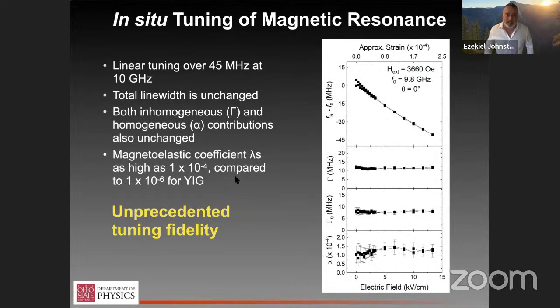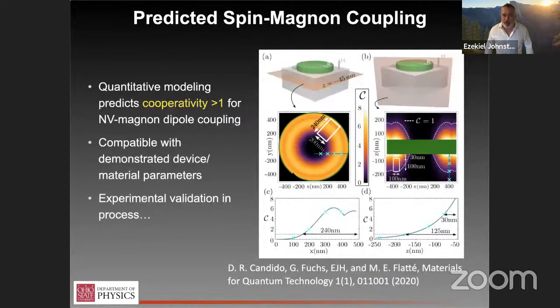And so in fact, this metric that we're sort of inventing here of 4 to 5 line widths of tuning with strain is at the leading edge of the maximum strain tuning that can be seen in any system. So this is pretty powerful, and as I'll show in a second, we believe that dynamic range is in fact limited by the piezo, not the material. And so this is a little bit out of chronological order.